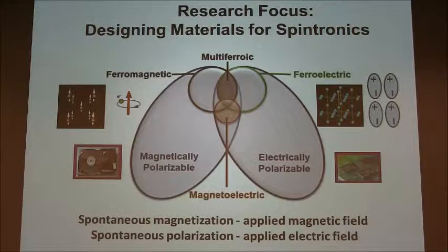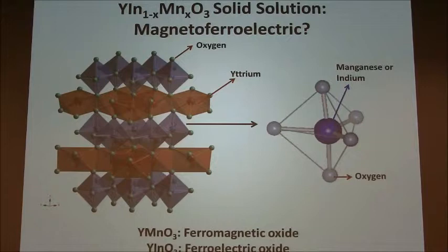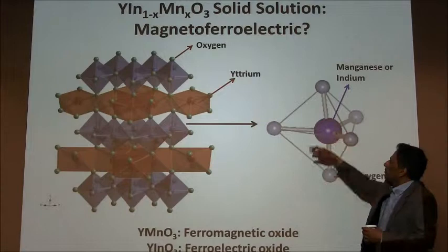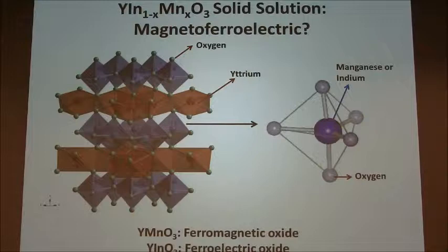So the materials we're working on are interesting oxides. We are trying to create a material by mixing two different atoms in the crystal structure. One is, in the case of manganese and indium, in a site which is surrounded by 5 oxygens. So when we try to design these materials, we thought by simply mixing a material which is ferromagnetic and also a ferroelectric, that means the capacitor material, we can come up with a new way of creating multi-ferroics or multifunctional materials. So that is the whole idea of doing this research.